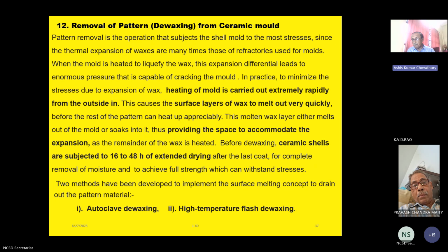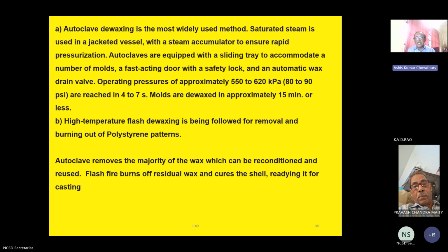Two methods have been developed to implement the surface melting concept to drain out the pattern material: autoclave dewaxing and high temperature flash dewaxing. In autoclave dewaxing, the most widely used method, saturated steam is supplied to jacketed vessels with a steam accumulator to ensure rapid pressurization. Autoclaves are equipped with a sliding tray to accommodate a number of molds, a fast-acting door with a safety lock, and an automated wax drain valve. Operating pressure is 550 to 620 kPa or 80 to 90 psi, and is reached within 4 to 7 seconds. The molds are dewaxed in approximately 15 minutes or less.